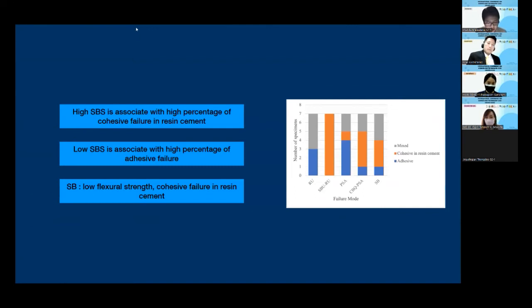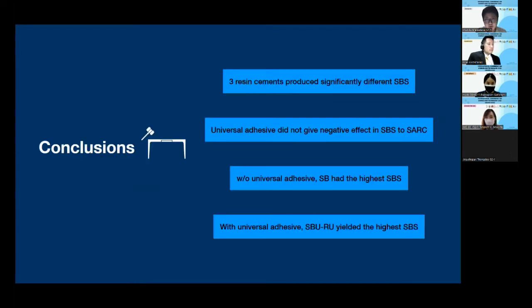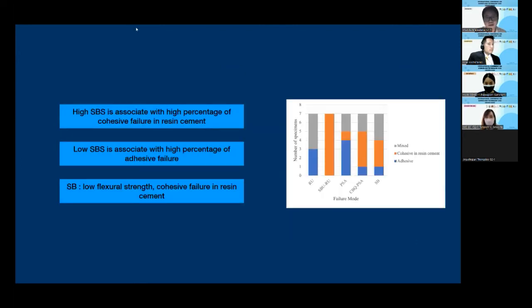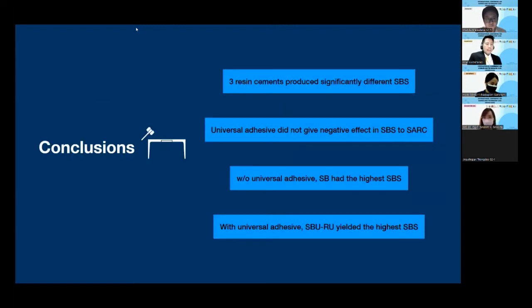In general, the high shear bond strength groups mostly show cohesive failure, and the low shear bond strength groups predominantly show adhesive and mixed failure. Superbond C&B benefits from anti-adhesion with a strong bond, but the low flexural strength property could lead to cohesive breakdown in the resin cement.